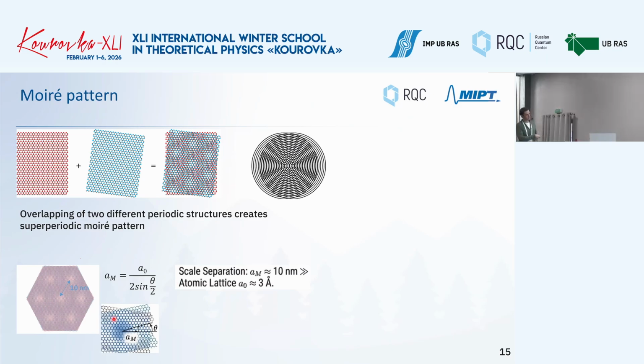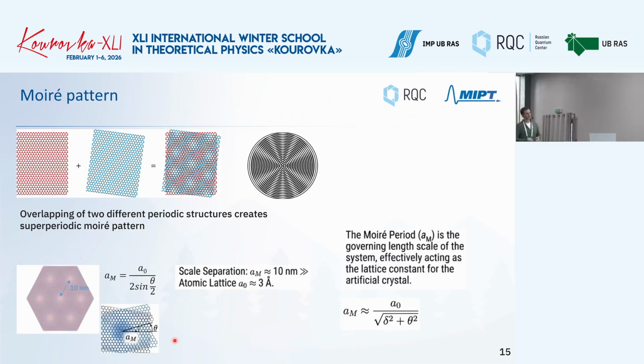The scale separation in this case, you see, is around 10 nanometers, and the atomic scale is like 3 angstrom. But if you have two different types of materials, if you are making a heterostructure, it will also depend on this extra value of the mismatch of the lattice constants. So by changing the angle or just choosing materials with some specific atomic lattices, you can create a new length scale, your new artificial crystal. And you can control it just by angles.